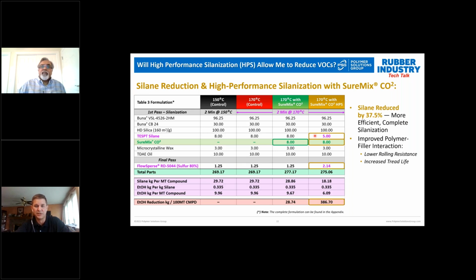So that's exactly what we tested here, which led to the concept of what we call high performance silanization. In this formula, you see we have a silica tread solution SBR, polybutadiene with 100 parts of HD silica and TESPT, so Si69 type silane. And we did silanization in a control compound at 150 degrees C, and then in a test compound at 170 degrees C.